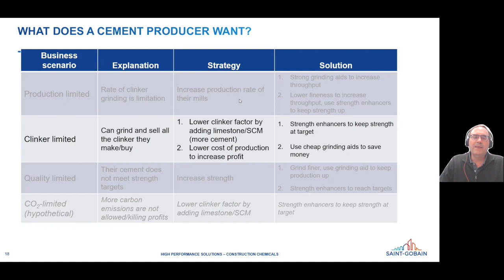Another situation that the cement manufacturer could find themselves in is called clinker limited. So this is kind of the opposite case. In this case, they have plenty of grinding capacity. They can grind all of the clinker that they have available. So in this case, being able to grind it faster is not really as much of an advantage, right? They're going to end up with the same amount of cement to sell at the end of the day because they have all this grinding capacity. So what makes a lot of sense in this case is to dilute their cement with something cheaper, so limestone or a byproduct material, secondary cementing material. This way they can make more cement from the same amount of clinker. And when you do that, you get lower strength. So this is where a strength enhancer is very valuable.